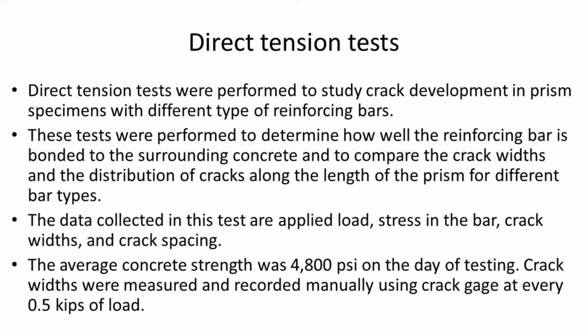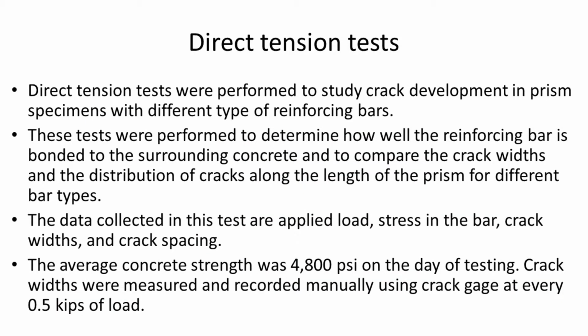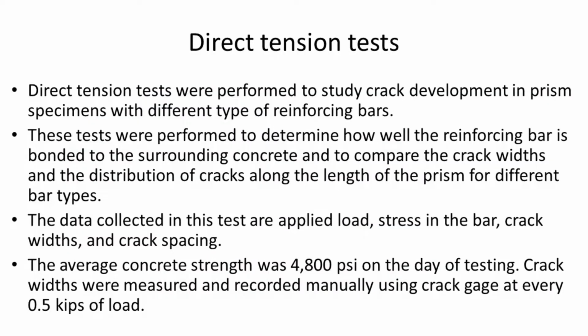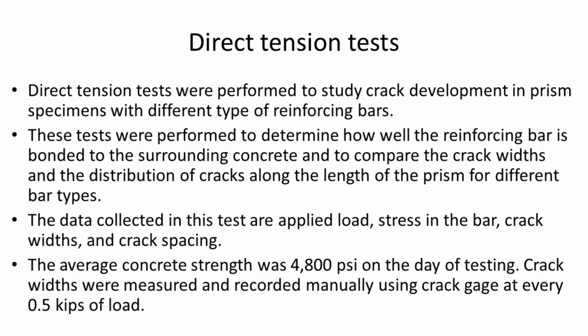Another grouping of tests called direct tension tests, and there were several different kinds of these direct tension tests performed, again, similar in prism specimens with different types of reinforcing bars, same ones, and the test performed determined how well the reinforcing bars bonded to the surrounding concrete, and compared the crack widths and the distribution of crack widths. So it's not only about the distribution of crack widths, but how close they are together, but the number of them as well. So the data collected was applied load, stress in the bar, crack widths, and crack spacing. So all important in how chlorides eventually are going to migrate to the surface of the rebar. Ultimately.